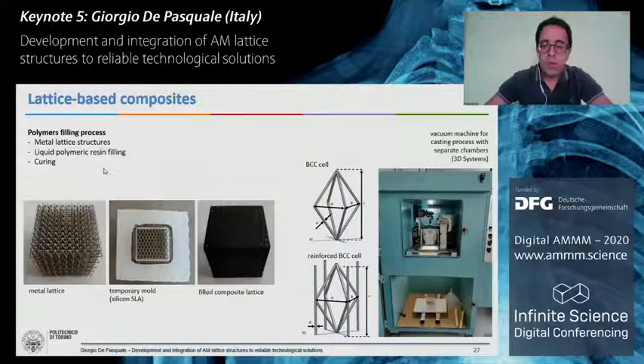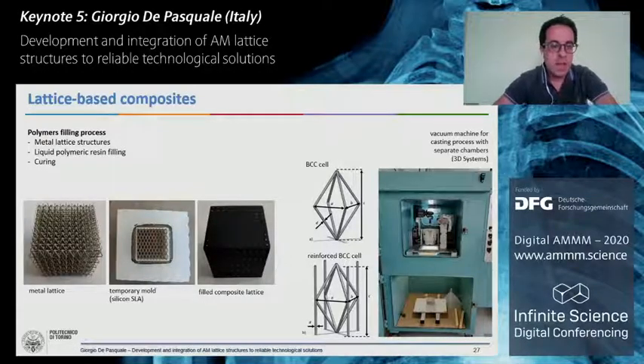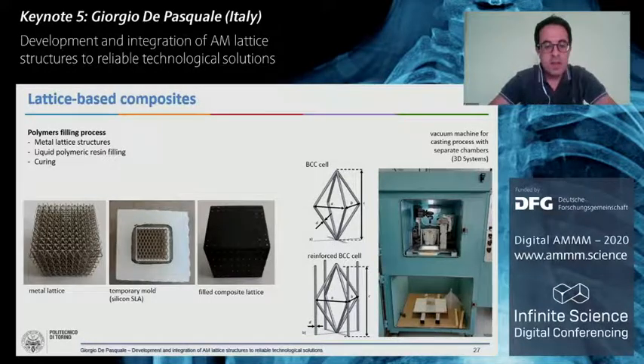I want to conclude with two quite new applications of lattice structures. The first one is composites based on filling lattice structures with polymers. This technology is pretty new. We tried to make these samples with good results by creating a temporary mold made in silicon, and by filling our lattice structure, in this case a metal lattice structure made with aluminum, with liquid polymeric resin, followed by a curing. So what we get is a polymer with a sort of reinforcement inside, provided by the lattice structure.